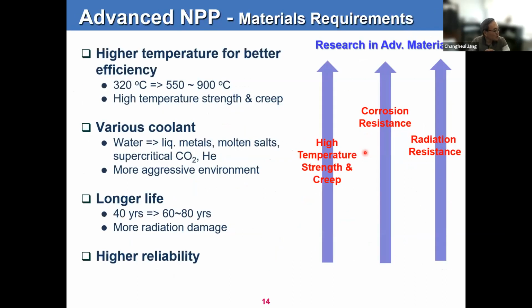So in those advanced nuclear reactors, including the light water reactors or non-water based reactors, all of the new designs are aiming for better efficiency. To achieve a better efficiency, as everybody knows, you have to increase the temperature of your system. Right now, the current reactor is operating at somewhere around 320 degrees centigrade. But for the advanced reactors, your temperature will be somewhere around 550 to 900 degrees centigrade. And because of that, you should have the proper material that can have a high temperature strength and also the proper corrosion resistance at those temperatures.